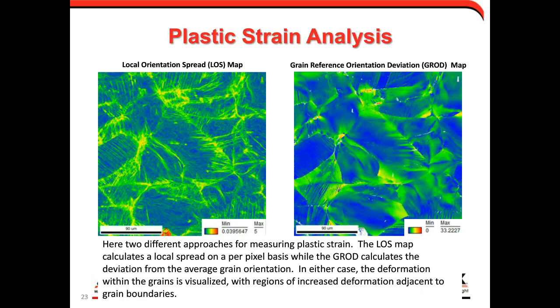These are maps where we're trying to show the distribution of plastic strain. Here are two different approaches. The first is what's called a local orientation spread map, which is shown on the left. This looks at the misorientation in a local kernel of points. These are on a scale where blue would be less plastic strain. As the colors go from blue into the yellows and greens and then to the reds, we see where there's more strain present. So we can see that strain is localized in certain grains and near certain grain boundaries.